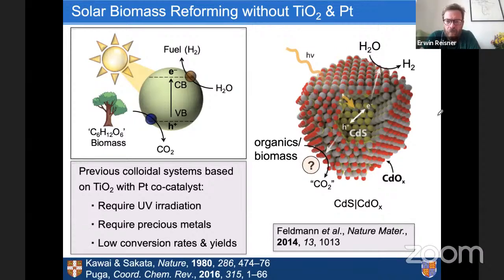And when we were looking for photocatalysts, light absorbers, we came across this publication by the Feldmann group in Munich. They had shown that if you take cadmium sulfide quantum dots, so quantum dots means a size of a couple of nanometers, and you dissolve them in an aqueous solution, they will form a nice colloidal solution. And if you bring this to an alkaline solution, they form this nice oxide hydroxide shell.